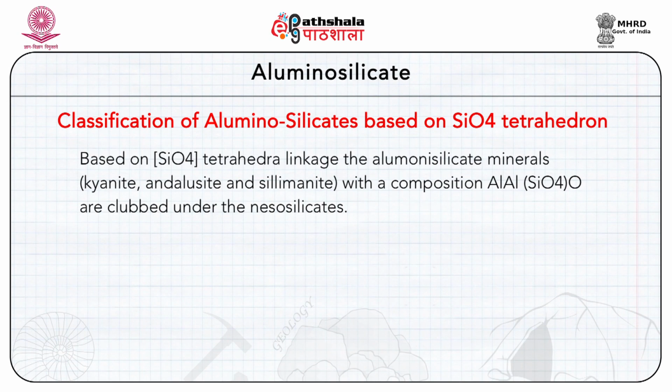In all cases, silicon is tetrahedrally coordinated by oxygen ions, resulting in discrete SiO4 units with 4 negative charge structural units. The remaining aluminum is in 6-fold coordination in kyanite, 5-fold coordination in andalusite and 4-fold coordination in sillimanite. These three minerals are of the same composition, but exist as different structures owing to different cross-linking and chain positioning depending on the temperature and pressure conditions, hence are considered polymorphs.